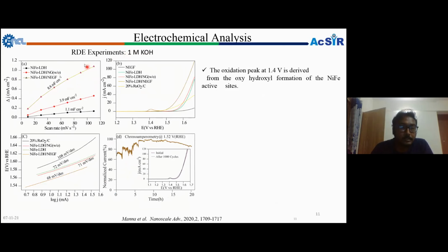So first we check the electrochemical surface area, that is the double layer capacitance measurement. The double layer capacitance is directly proportional to the electrochemical surface area of the material. Importantly, here you can see the nickel iron layered double hydroxide on its own, without any support, has a very low double layer capacitance value, like 1.1 millifarad per centimeter square. But in presence of the support, like nitrogen doped graphene, that is without the freeze drying system, already shown